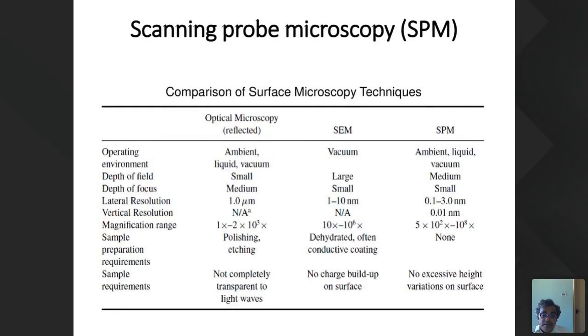If you compare the electron microscope and the scanning probe microscope, mostly the scanning electron microscope needs a vacuum atmosphere, whereas SPM is not like that. You don't need a vacuum; ambient conditions are also possible. The resolution is very high: 0.1 nanometer lateral resolution is possible, and the vertical resolution is 0.01 nanometer. That means atomic resolution, even less than the atom's size. No excessive height variations on the surface are allowed in the scanning probe and tunneling microscope.